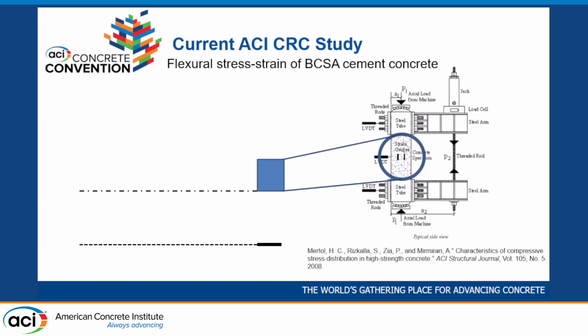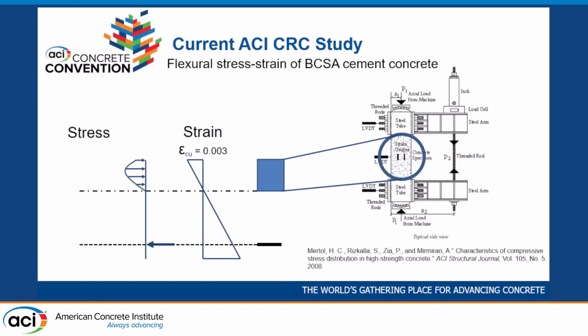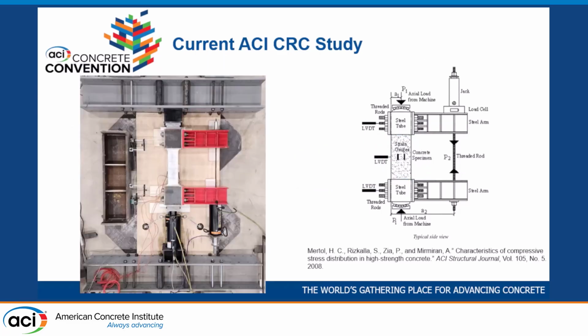The idea is we put a big axial load on the specimen and then we apply a load over here to put a moment in the concrete. This concrete portion is meant to represent the top part of our concrete stress strain diagram for a beam, the part of the concrete that varies from 0 strain up to 0.003, the ultimate compression strain. We know the stress distribution looks something like this, and we estimate it with this. So we're seeing if BCSA works the same way as Portland cement, if these parameters also work for BCSA cement. So there's what our setup looks like.